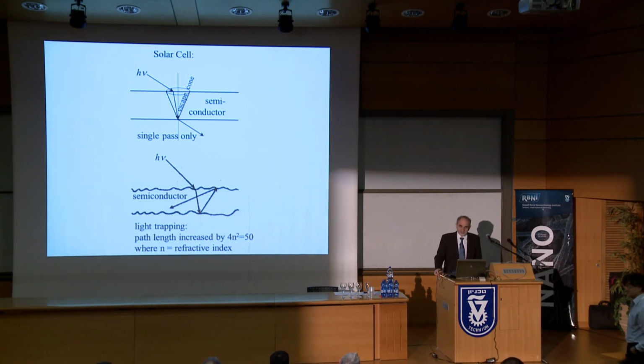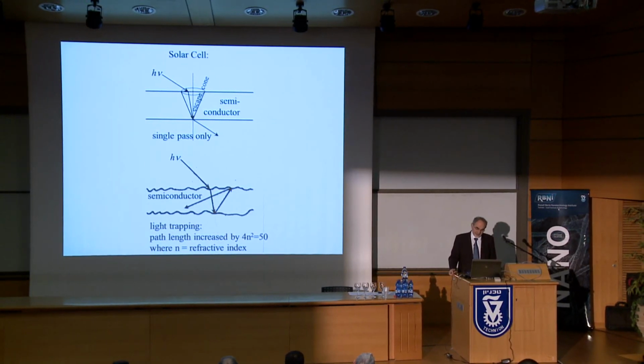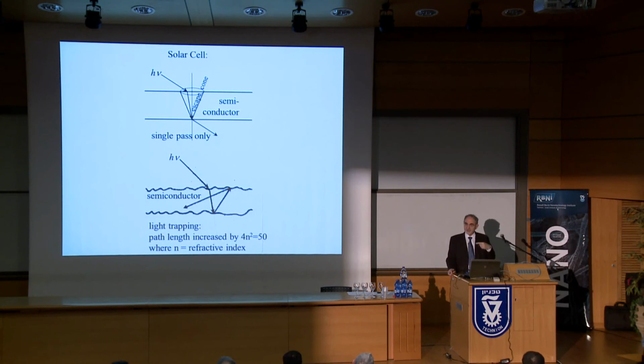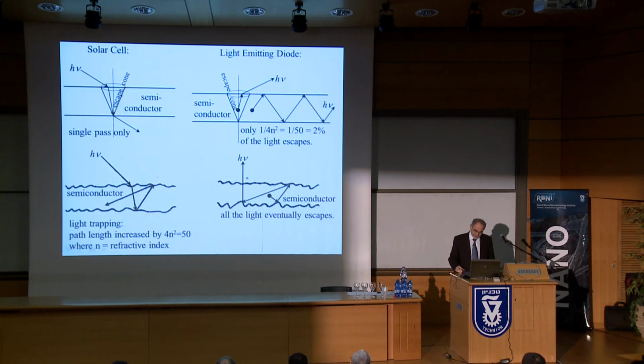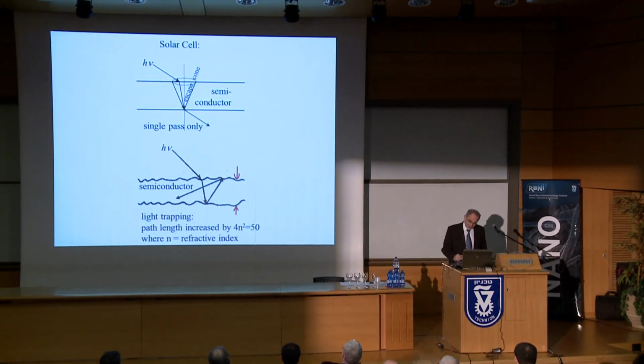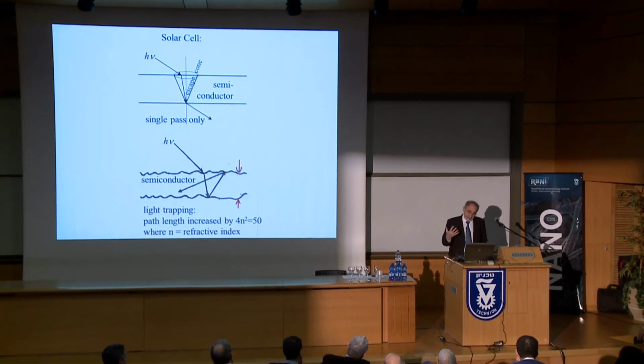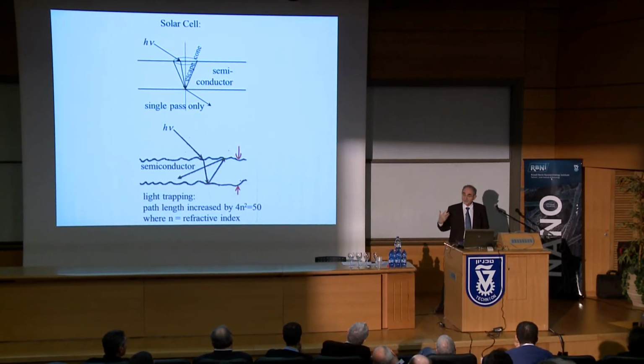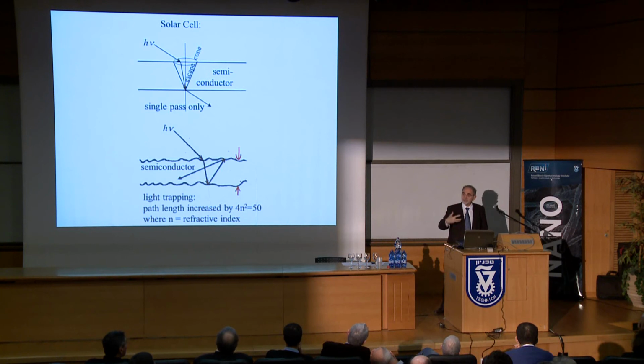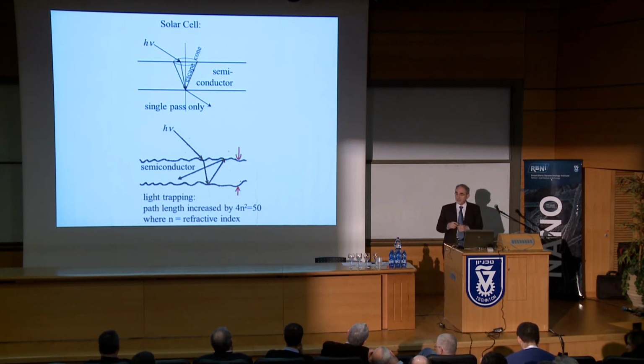Okay, so the question, it's kind of a subtle question. It has to do with the fact that optical absorbing materials have a dipole matrix element, and it's a vector, and it's pointing in a certain direction. This is certainly true of all semiconductors. But keep in mind, these are not nanostructures necessarily. These are actually bulk materials. The example I showed at the end could be 30, 40 microns thick. And when we talk about the optical absorption of silicon, we have already taken into account that some of the dipoles in the bulk material are pointing in an unfavorable direction. And so the known absorption coefficient of the indirect edge is already taking into account the very important effect that you're invoking. So it's something we have to live with.